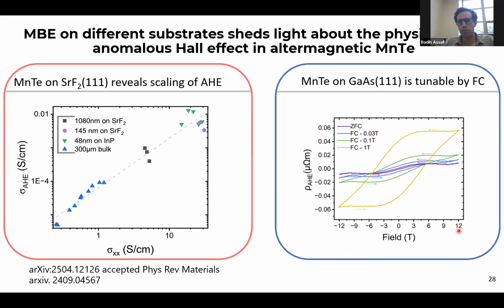I've showed you that when you grow manganese telluride by MBE on various substrates, the behavior of its anomalous Hall effect is very sensitive to the details of its structural properties. When you grow it on strontium fluoride, which I believe is the ideal substrate, we end up with an anomalous Hall effect that's as predicted, and that follows the scaling law expected for non-metallic materials. On the other hand, when we grow it on gallium arsenide and subject it to thermal strain, and when it hosts defects that are likely a result of the lattice mismatch on the substrate, we get this interesting and yet tunable